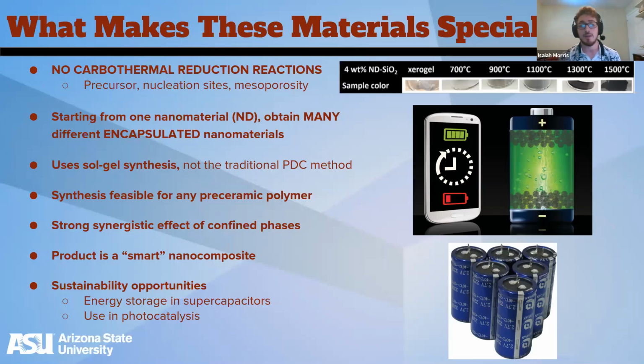It's also important to note that we used sol-gel synthesis and not the traditional PDC method, whereas the latter involves a separate step for cross-linking, as sol-gel synthesis does it all in one fell swoop. And the synthesis should be feasible for any pre-ceramic polymer, where these composites will still exhibit that same strong synergistic effect of these confined phases. And the product will be a smart nanocomposite with multiple opportunities, especially in sustainability when it comes to energy storage and the uses in photocatalysis and such processes like that.